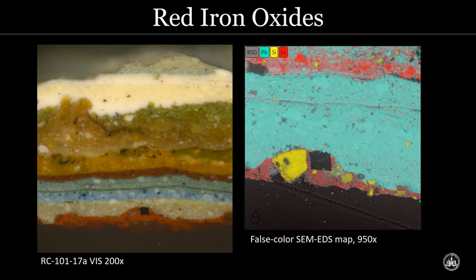So I analyzed it with multiple techniques, including SEM EDS mapping, where I can actually ask the software to make it red where it sees iron and make it light blue where it sees lead, etc. And so what you're seeing here on the right is a false color SEM EDS map of this area. And what we see is that certainly that early red-brown paint is rich in iron and also has large silicon particles associated with it. So this is definitely a red iron oxide. We did not detect any vermilion, which contains mercury and sulfur. So just a very, very pure, very bright red form of iron oxide.